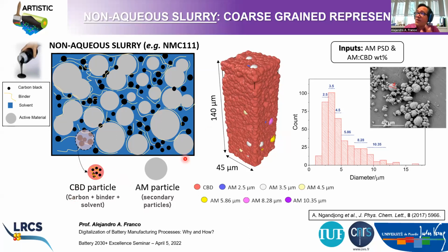And this particle contains carbon, binder, and solvent. We do it in this way because if you start to describe all the atoms and molecules present in this system, you will need a very huge computational cost in order to solve the system of equations that will allow you to predict the slurry structure, right? That's why we simplify the system with this coarse graining approach. And instead of representing the interaction between atoms or molecules, we will represent interaction between these effective particles of grain, active material, and CBD.